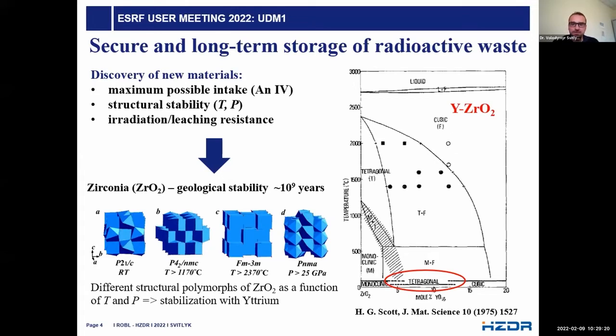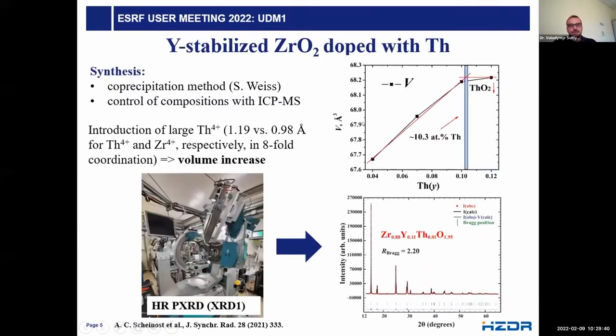Today we'll speak about doping with yttrium. And I will start with tetragonal stabilized zirconia. It can be obtained with yttrium content from around 5 to 15% when you quench from the high temperature region where the cubic phase exists. Synthesis was done in collaboration with my colleagues in Germany, at HZDR, Dresden, Institute of Resource Ecology. Synthesis was done with the co-precipitation method.